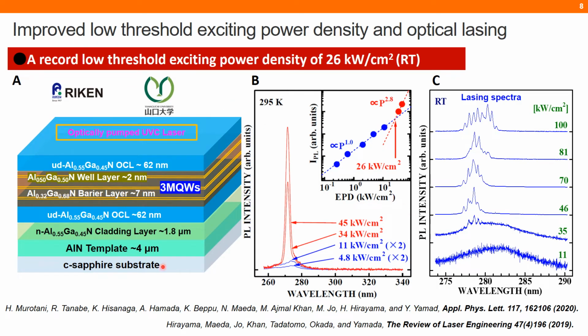First we grew the optically pumped laser diode structure on a 4 micrometer thick aluminum nitride template. A very thin 1.8 micron AlGaN cladding layer was introduced, which is contrary to the Meijo University work where they use 9 micrometers. And then here we grow the quantum well structure, and then the undoped-AlGaN OCL, and here is the undoped OCL. So the laser diode structure was like this.